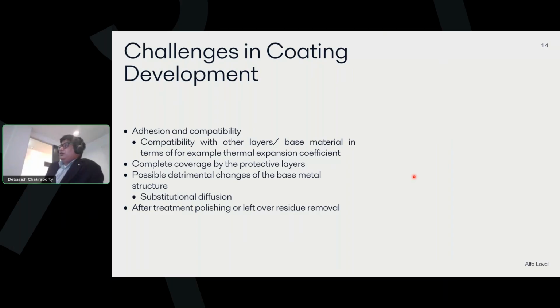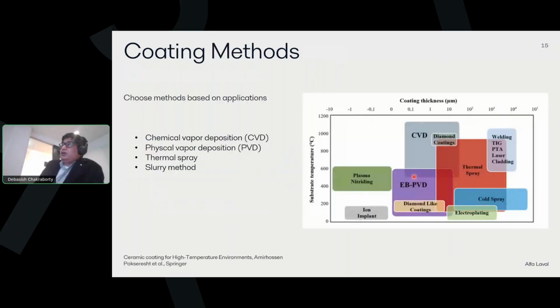And then there are possible detrimental changes in the base metal by substituting the elements of the base metal with the coating material. And polishing after treatment could also pose a lot of challenges. There are different methods available: chemical vapor deposition, physical vapor deposition, thermal spray, and the slurry method, and one could choose based on what kind of thickness and geometry one is looking for.